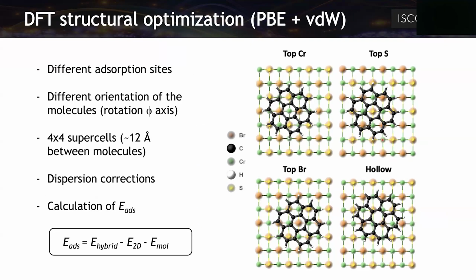To do this kind of calculation, we have to test different adsorption sites in the material and also different orientations of the molecules. These are expensive calculations. We need to work with large supercells, in this case 4x4 supercells, to ensure a distance of around 12 angstroms between the molecules, and we have to add also dispersion corrections. And with this, we calculate the adsorption energy from the different positions of the molecule on top of a chromium ion, on top of sulfur, top of bromide, hollow. So we have to test all these possibilities.